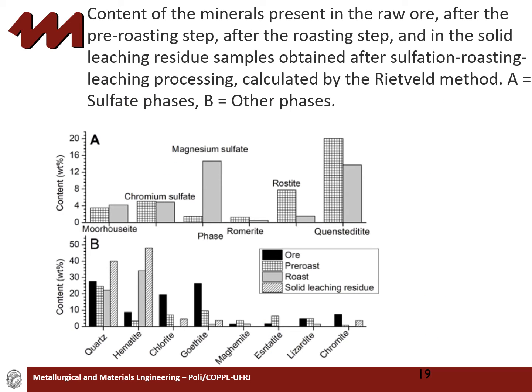The content of the minerals present in the sample during each step of the processing can be observed in this figure. The main sulfate phases found after the pre-roasting and roasting heat treatment were Moorhouseite, which is the nickel and cobalt carrier, magnesium sulfate, chromium sulfate, Quensteditite, and Rostite.